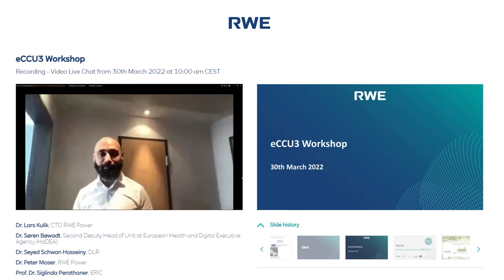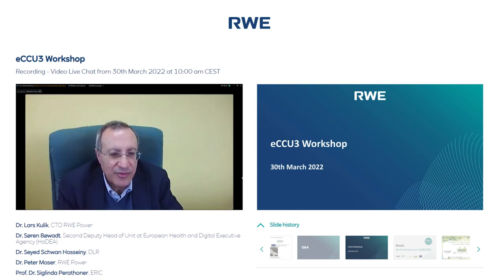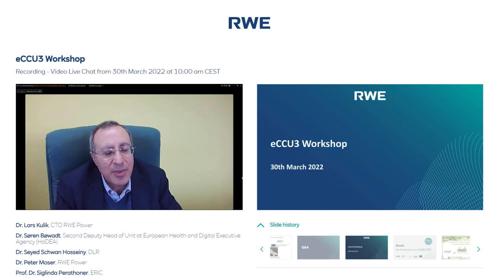We want to avoid, let's say, critical raw materials like precious metal electrocatalysts, like iridium and ruthenium oxide. Of course, using iridium and ruthenium oxide, we have a strong enhancement of the oxygen evolution reaction, but there is not much availability of these materials, and we need to decrease the capital costs for this technology for sure. And we also wanted to exclude materials that are in the critical raw materials list from the European Commission, like cobalt and rare earth elements. So this should be avoided because there is not only a problem of cost, but also availability. We are depending on other countries for the supply of materials.